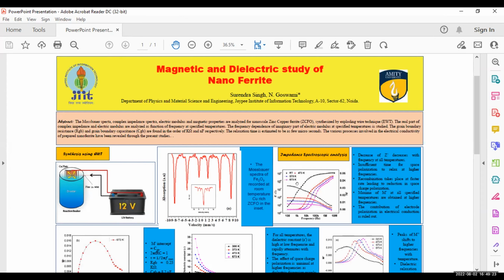And then we have the AC conductivity study versus frequency. This is governed by the relation of AC conductivity, that is Jonscher. We'll study this later with the Jonscher plot also. The AC conductivity of the nanoferrite is increasing with frequency. Therefore it is confirmed that hopping charges are actually causing the conductivity of the material.